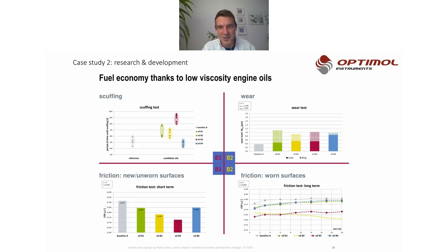So at the end of those tests, made within 2 weeks, you are able to say, okay, if there is a need to implement low viscosity oils and the coating due to friction reduction, the most promising are the red and the yellow one. Within 2 weeks, without any diesel fuel, it was way beneficial, and this method is implemented at the Volkswagen Group. So they are investigating their solutions with this method and with the machines of Optimol.